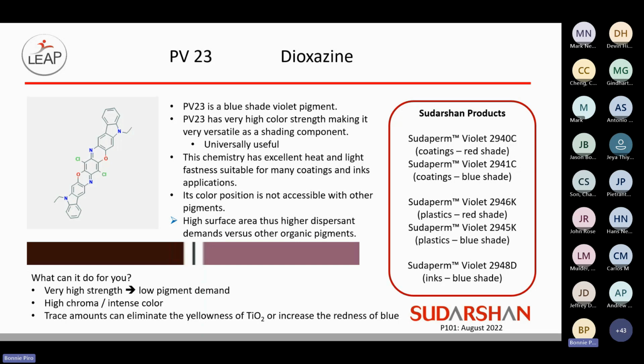In terms of formulation, it does have a good role in white coatings to reduce the yellowness of those particular ones. So very trace amounts can really brighten the white coating. And also with respect to blues, a very trace amount can really increase that redness of a blue if that's the direction that you need to go.